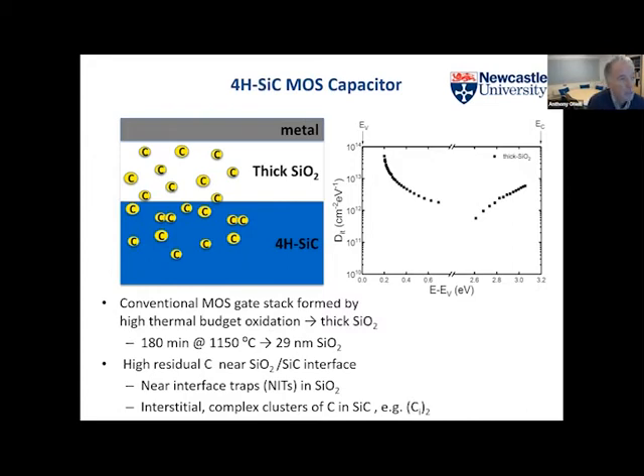And so if you are to look at the defects at this interface, they're pretty enormous compared with what you would find in something like silicon because of these carbon related defects, for example. So this is a plot of the density of interface traps at that interface as you go through from the valence band to the conduction band. And you can see the numbers up here are up at around 10 to the 13, 10 to the 14, which is really just too bad. And that's why I expect you get the very poor mobilities.